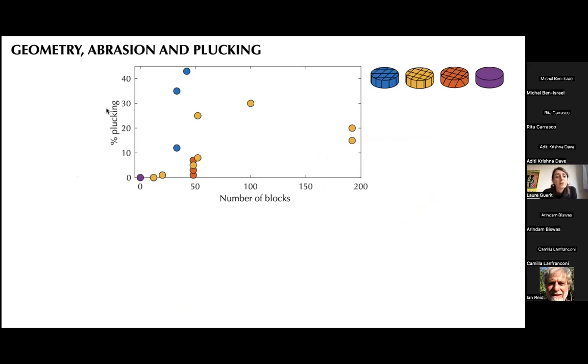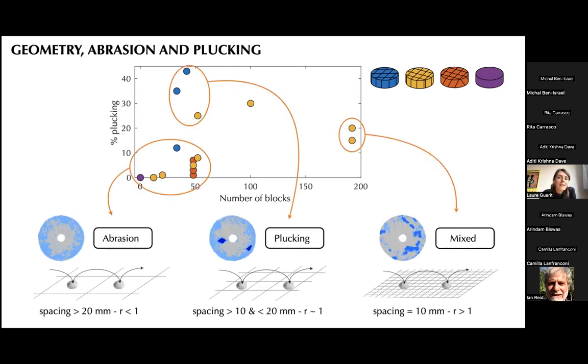So you have here the contribution of plucking with respect to the number of blocks for various experiments. And please remember that plucking is always associated with high erosion rate. So I could change here this axis for average erosion rate, and we would have more or less a similar curve. And so what we observe is this sharp increase in plucking contribution until about 50 blocks, and then this clear decrease. And this is how we explain it.